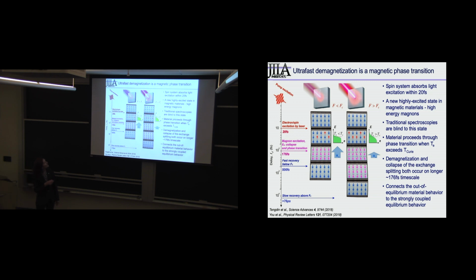But if you heat more strongly, then there are a lot of electrons above the Fermi level. You can have a lot of spin flips, and now this is a high energy magnon state. You don't have that many, but then as these relax, you have a high density of low energy magnons. This would be the state you would make by normally heating the magnet. And of course, it is nice that it shows the out of equilibrium behavior relaxes to a similar state, even though you would never make this state by just direct heating.